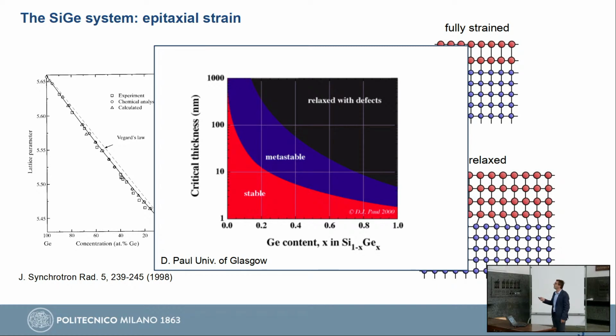And if you make this balance, you obtain this curve, which tells you, as a function of the germanium content, how thin your layer needs to be to be fully strained. So if it's pure germanium, this would be a few nanometers. If it's 20% silicon germanium, this can be 10 nanometers or more. So in any case, the order of magnitude is a few nanometers thickness. So we say that we can have a fully strained configuration and a fully relaxed one. You can also have situations in between, but this is what we typically want to have in application.